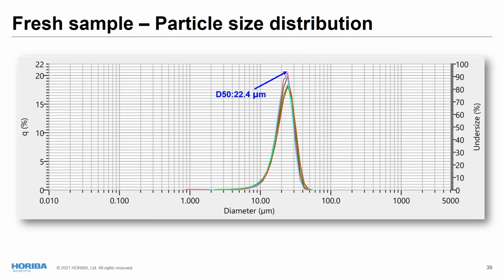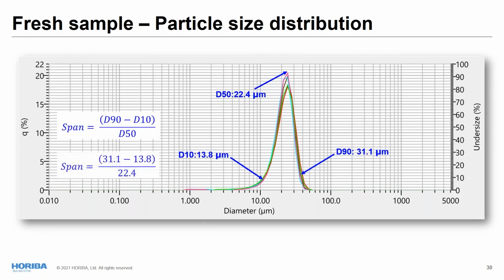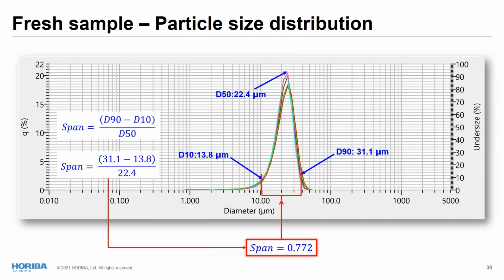ISO also recommends that we follow the limits from 10% of your sample, which reflects the lower portion of your distribution, and the larger particles, the larger portion of your distribution, the D90, which in this case was 31.1 microns. So when you have 3 values, we can calculate something called span. Span is a relation of the D10, D90, and D50 that gives us a dimensionless number that reflects how broad your particle size distribution is. All 4 numbers are very important for you to keep track of the performance of your material, because you can have very different materials with the same D50, but with very different D10 and D90s, which will be reflected in the span.